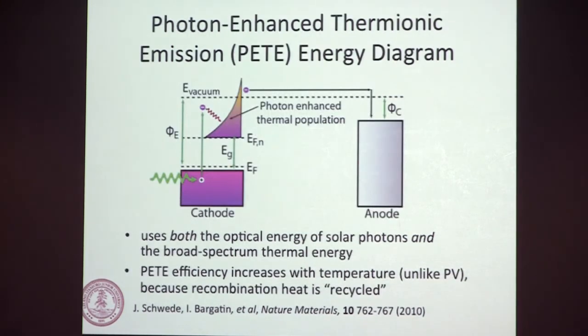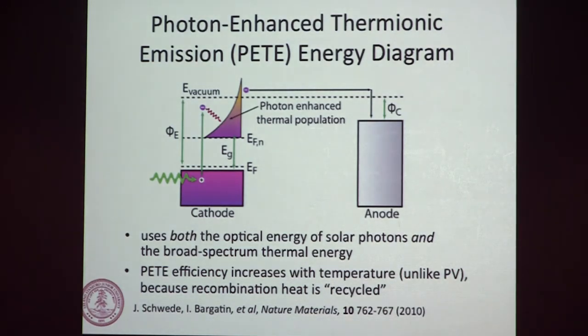We have, for those that have seen these band diagrams, a semiconductor now. We have a band gap, and so we have a quantum boost if you're at the right wavelength to get enough energy over the band gap, and not enough to emit direct from the valence band out. You end up in the conduction band where you thermalize, but you have an easier hop over the electron affinity than you do off the work function. So you have a lower barrier. It's kind of a two-step process, and so you use the optical energy and the thermal energy. Thermal energy is not lost. The device wants to be hot, unlike a photovoltaic cell, and so you basically are recycling this heat. The anode is still a metal. Igor has some great ideas on looking at that as a different material as well.